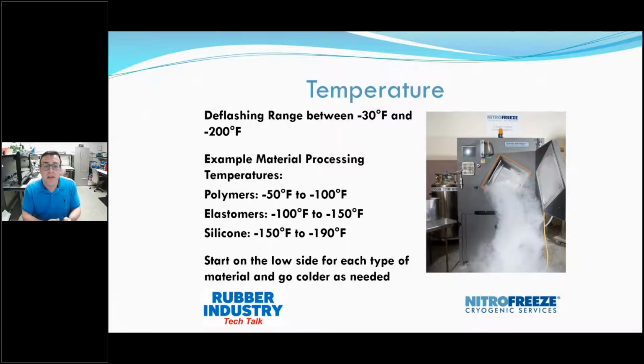What I recommend is that, in terms of temperature, you work in increments of 10 degrees Fahrenheit and go colder as needed. A lot of it has to do with geometry again. If you have a small O-ring, you could run at -170 degrees Fahrenheit. If you have a larger part that is thicker, you would probably run that silicone part closer to -180 to -190. So this is where geometry comes into play with temperature.